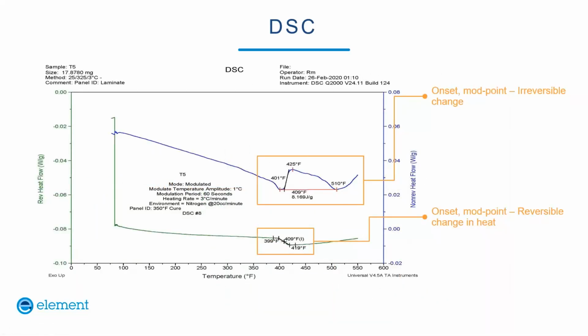Modulated DSC provides more resolution, and you can see the reversible changes in enthalpy. The instrument heats and cools in oscillation while gradually heating the specimen. So it'll be heating, and it'll go up and down 1 degree C per minute, and then that'll ramp up. And then the instrument measures the reversible and irreversible changes, and it's calculated and plotted. So the top curve, in this case, is an irreversible change. And what's happening here is there's some kind of reaction going on. It's an exothermic reaction, so it could be a cure, or it could even be a degradation reaction. And we can plot the peak points and the onset of that.